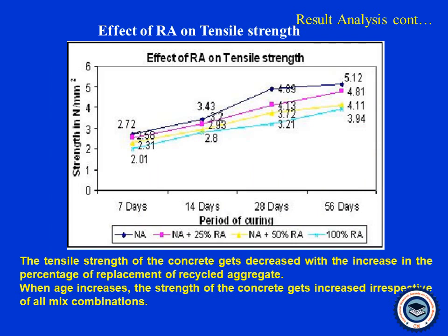Similar sort of results was obtained in the tensile strength. Here also only a lesser reduction in tensile strength was observed at the earlier ages, and the percentage reduction in the tensile strength of concrete was observed as 5% to 26% for the 25 to 100% replacement. And at the age of 28 days, it increased to 15 to 35% for 25% to 100% replacement. But the percentage decrement in strength gets reduced when the age of the concrete increased. At the age of 56 days, it was observed as 6%, 20% and 23% for 25, 50 and 100% aggregate replacements respectively.